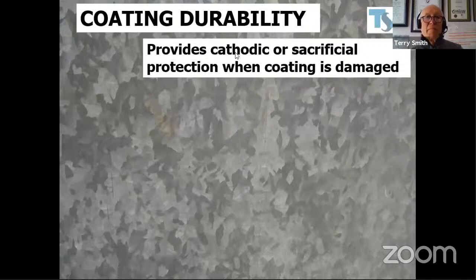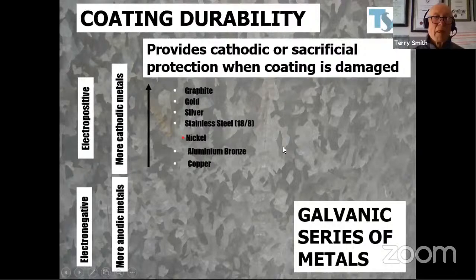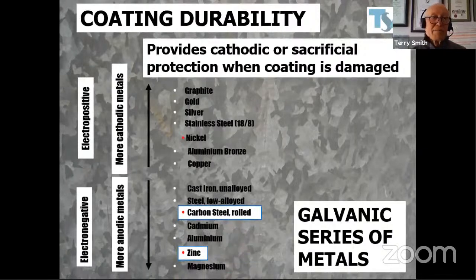Coating durability provides cathodic or sacrificial protection when the coating is damaged. As Simon and Martin talked about, you have the electropositive materials like graphite, gold, and silver, and electronegative materials down the bottom here. You see zinc and carbon steel. So zinc sacrifices itself to protect carbon steel.